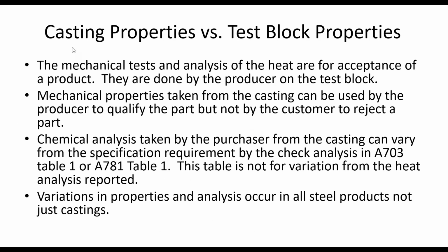So just in summary, if we look at casting properties versus test blocks, the mechanical tests and analysis are for the acceptance of the thing. They're done by the producer. They're not done by you. The mechanical properties taken from the castings can be used by me, the producer, to qualify the part, but you can't use them to reject the part. So if I don't have enough test material and I cut a chunk off your casting and weld material back on, I can use that on an expensive big casting to show that I met your properties. But if you take that same casting and cut it up and say that the properties are not in the casting, you cannot reject the part with those properties.